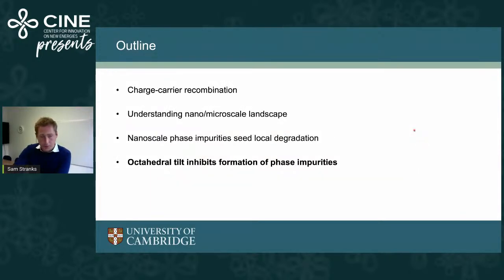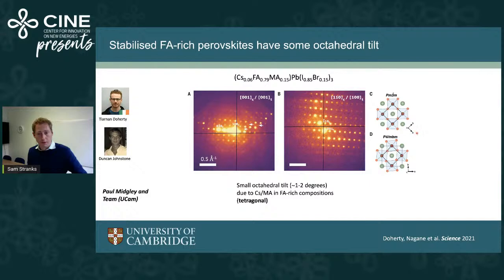Okay, so just in the last few minutes to wrap up, I want to just talk about where these phase impurities are coming from and why they're there. And the first thing I want to show is that these formamidinium-rich samples are actually tetragonal in phase. They're not actually cubic. And this is when we look at these scanning electron diffraction patterns, we can really quite nicely assign them because it's a scanning technique. We can move around and look at different zone axes of the crystal, even on the same film, and we can therefore more uniquely label or assign the symmetry and space group of this material.